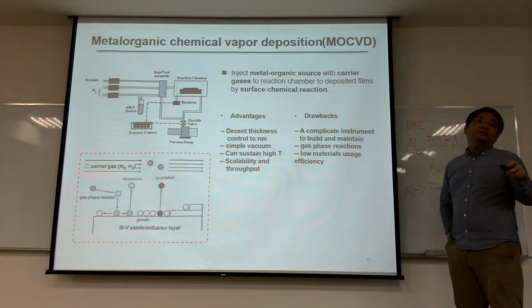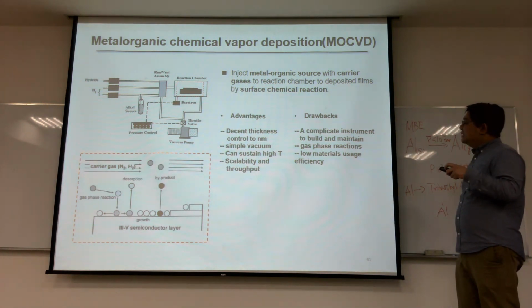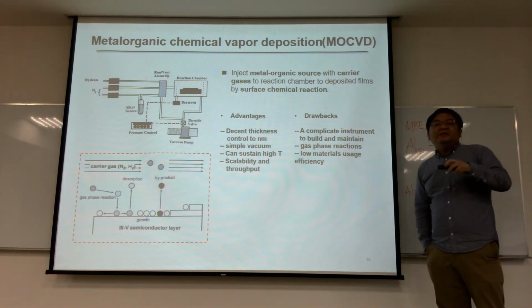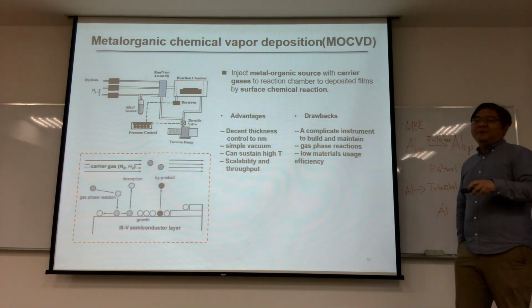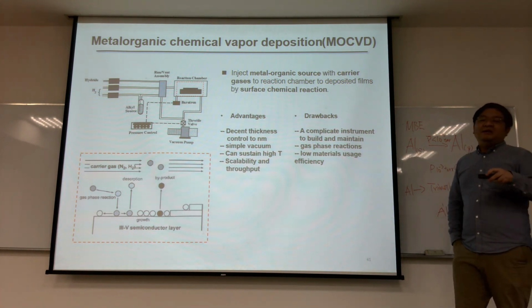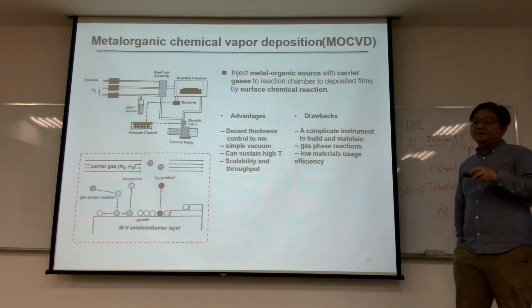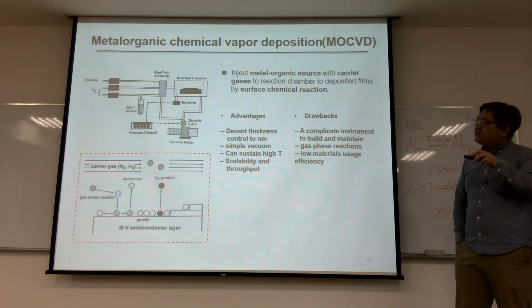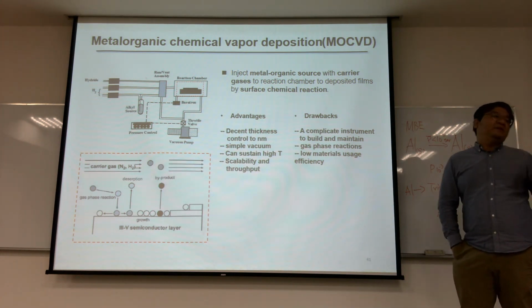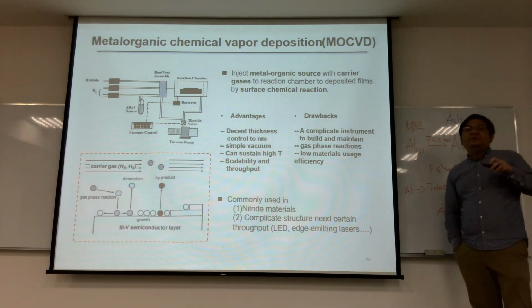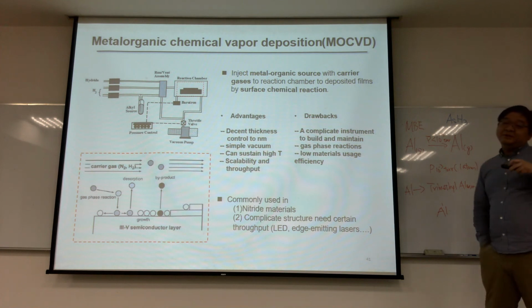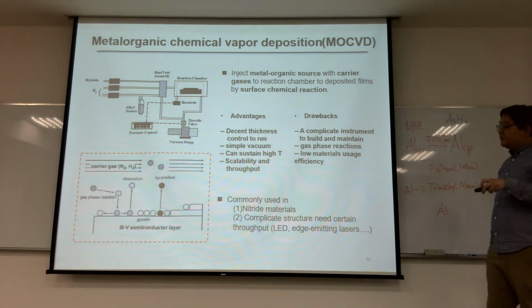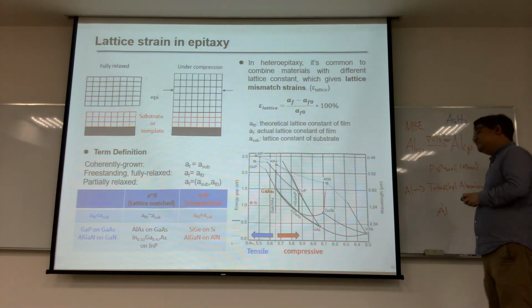But surely there's still some difficulty. For example, it is a complicated instrument to build and maintain. It's always a big issue that very few people in the university can really grow crystals by themselves. It's very difficult because you're involving so many chemicals, so there are many safety issues. For nitride materials, it's almost 100% MOCVD, because for some particular reason MBE cannot grow a good nitride material. That's another exception. And for complicated structures that need certain throughput and reproducibility, we also use MOCVD.